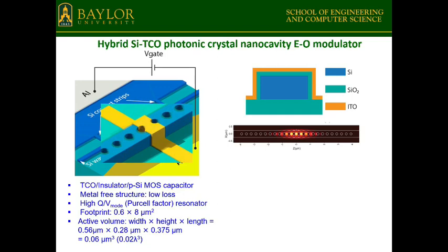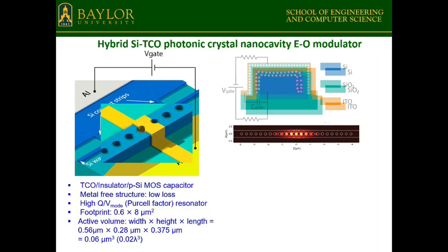But this alone cannot be a modulator. We have to put the electrode. So basically we use a transparent conductive oxide as an electrode on top of the cavity. And then we apply a voltage. So you can see electrons will accumulate in the transparent conductive oxide, holes will accumulate in silicon. That can change the refractive index of the material. If initially the cavity is on resonance, you apply voltage, it will be off resonance because the refractive index is changed. And then you can control the on and off, or control the transparency of the cavity. So you can build an optical modulator based on this.